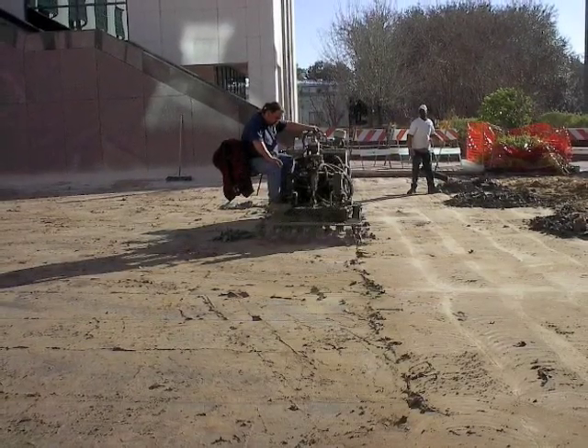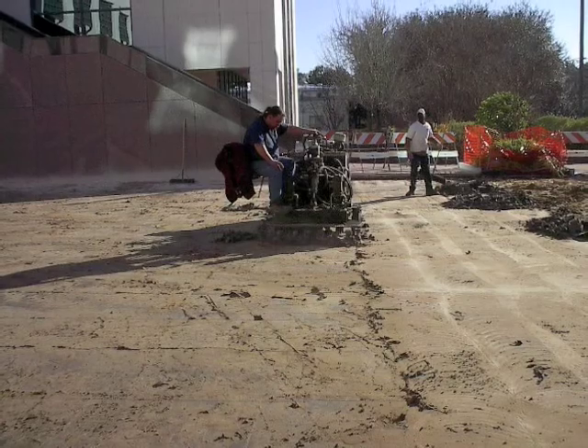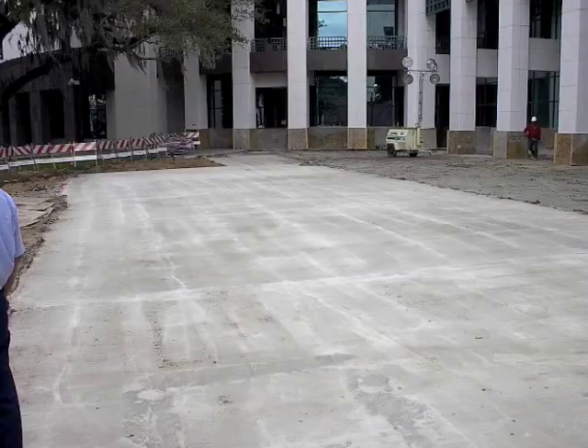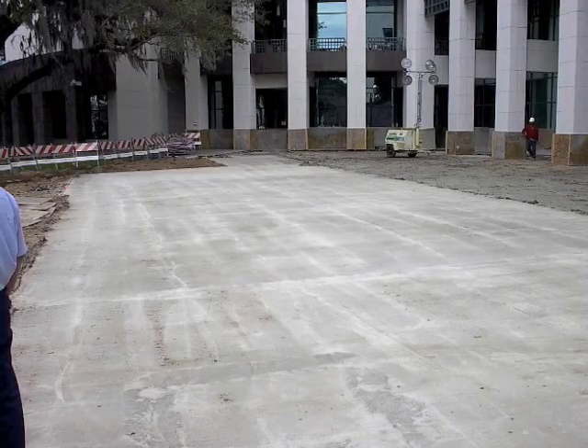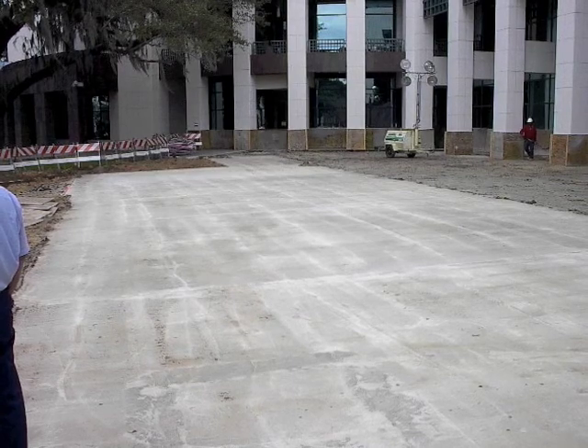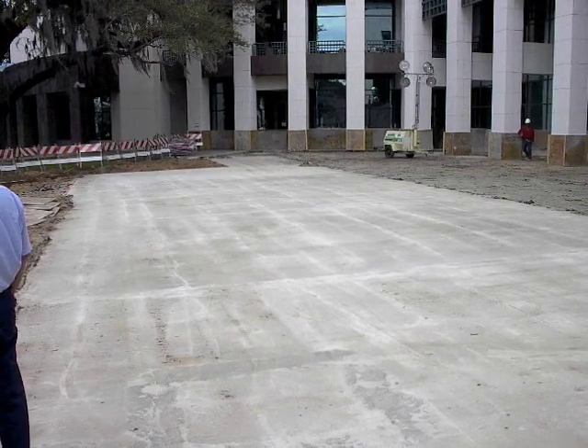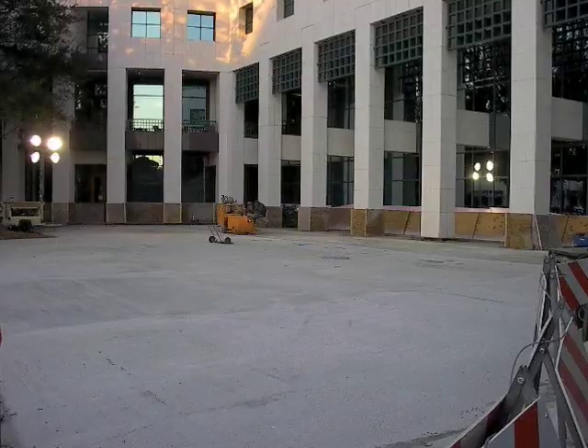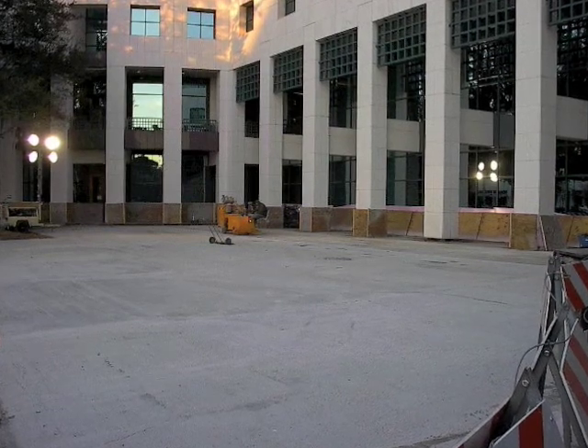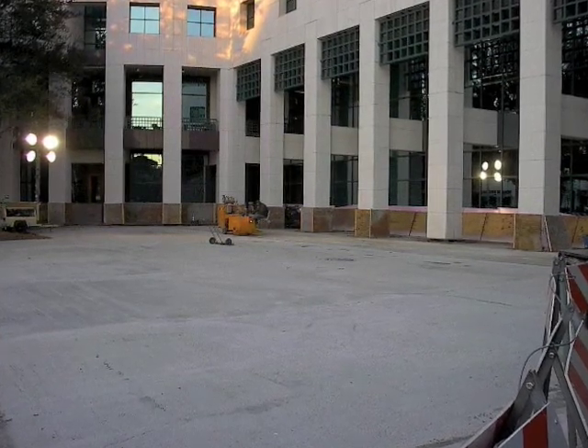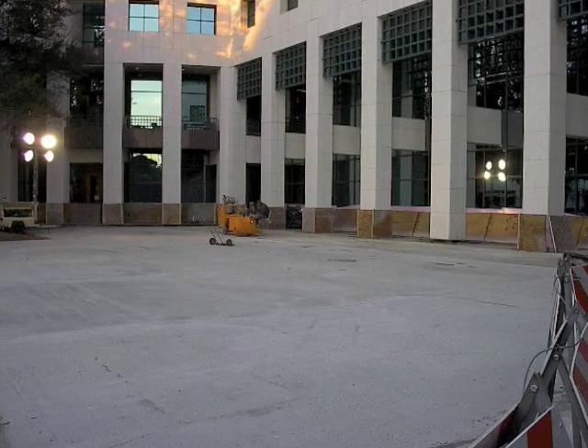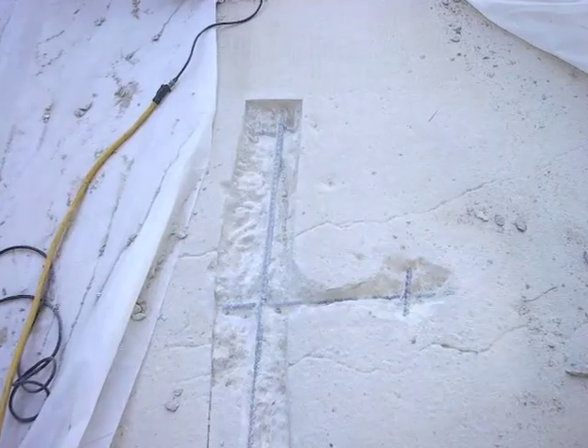Preparation of the concrete surface is critical in the application process of CFRP. After the removal of the lawn and waterproofing material, we removed excessive concrete paste through a shot blasting procedure. A thorough cleaning is required to remove any latent particles, and then the application of epoxy resin, or primer, provides a level surface profile for the CFRP material.